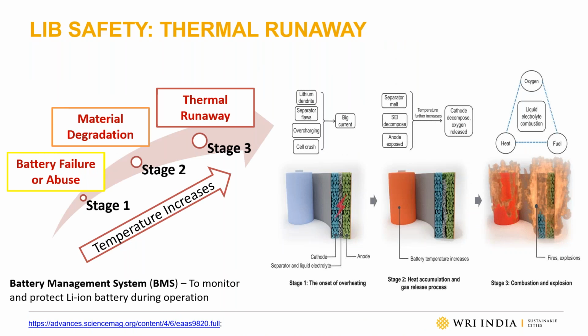So one of the major concerns is related to the safety of the lithium ion battery. I mentioned earlier that in lithium ion variants, there is a cathode electrode, cathode and anode, and in between we have a non-aqueous electrolyte, which is flammable. So any abuse condition or battery failure can lead to material degradation, which in turn can lead to thermal runaway. So what is thermal runaway? Thermal runaway is a catastrophic event causing uncontrolled temperature rise during cell operation and release of a large amount of heat energy.